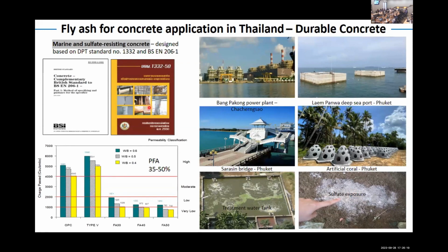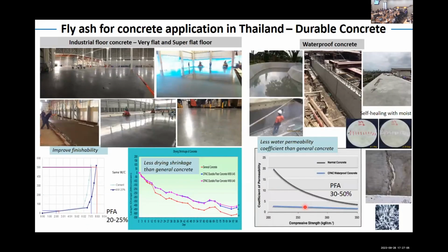And as Professor Smith mentioned, we have our own performance-based standard guideline for the design of durable structures in severe environments. So the benefit of fly ash for chloride content is that it can resist chloride very well. The chloride penetration is going to be low when you replace more fly ash and reduce the water-cement ratio. This is some projects used in Thailand, and also for sulfate resistance as well. Some water treatment tanks and some soil that have sulfate conditions. This is a benefit of fly ash for durability.